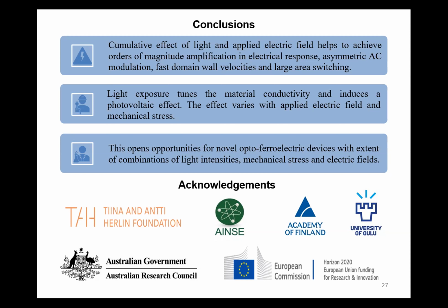I have a few. May I please take over the host role so people can hear? First, you showed those PFM images of the sample, and it was unlike PZT. We could not see the exact poling reversal. So why is that in such materials?